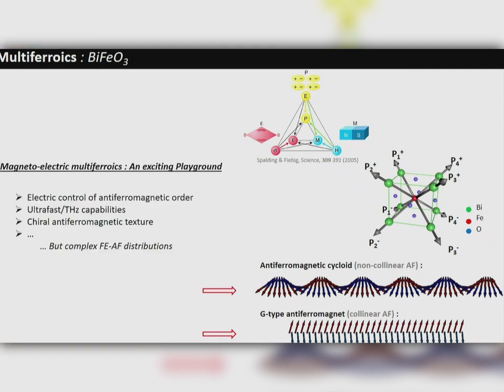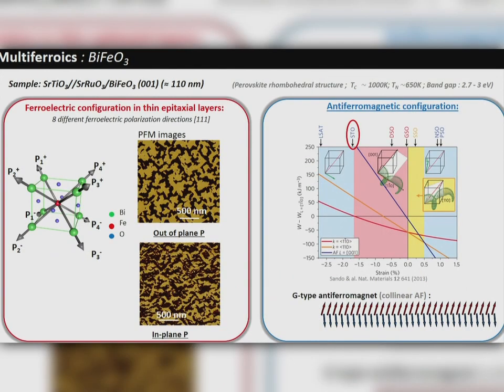And so to sum up about this system, it's definitely a quite rich playground for electric control of the antiferromagnetic order in one place. But what we also have to mention is that this bismuth ferrite also has a quite high frequency, as you will see by the end of the talk. It is known that it has antiferromagnetic resonances around 600 gigahertz, something like this. So on the other hand, it's kind of a complex textures. So here is the sample with which we're going to play today.